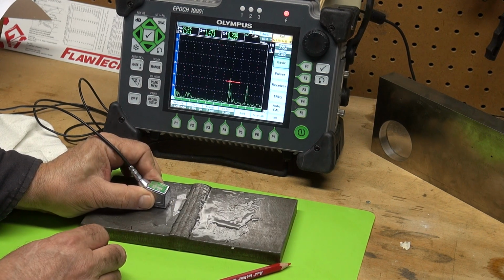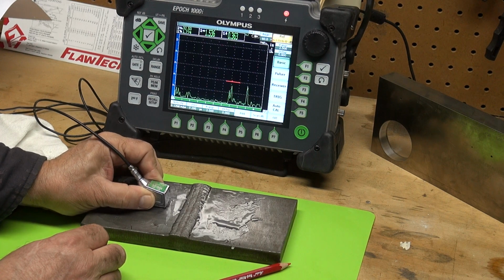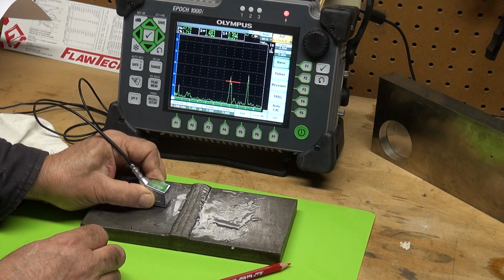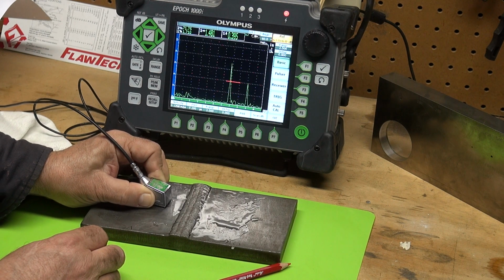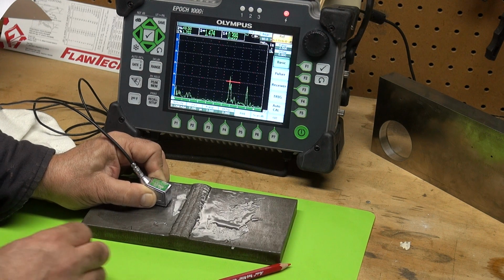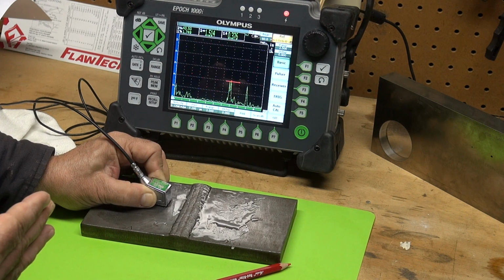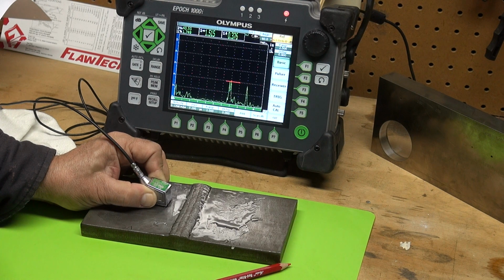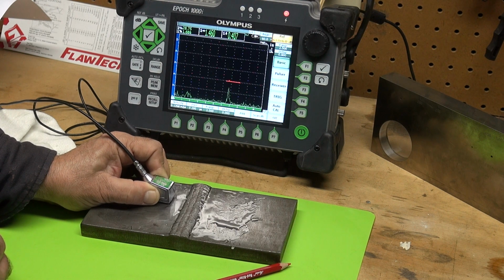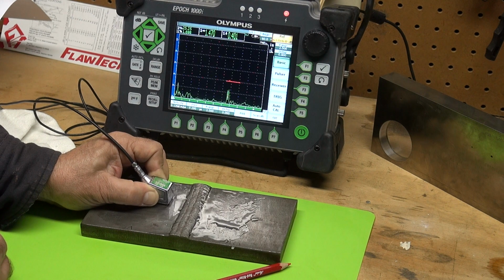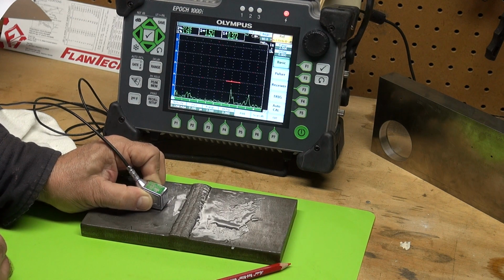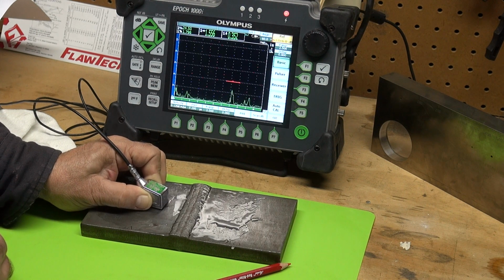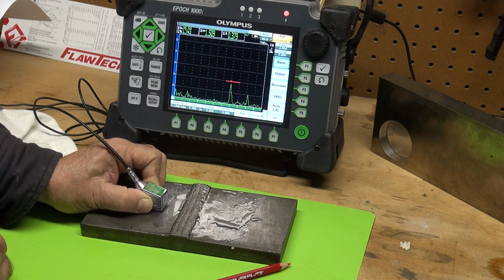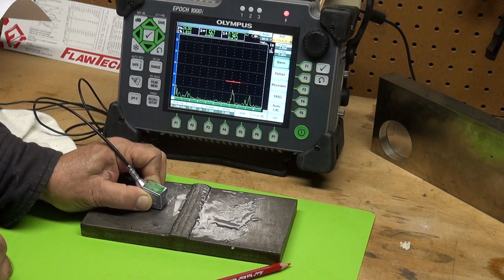See, that shows up pretty nice. But the reason you want to run a little bit hot, and there's a good representation of what slag inclusion looks like. But you always want to run a little bit hot, depending on your code, because then it will alert you to small indications in the weld, and then you can go back to your reference level to analyze them to see if they're significant or not. But this is a typical signal that you get from a slag inclusion.